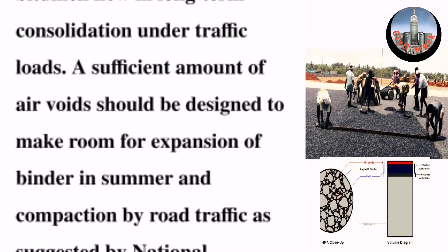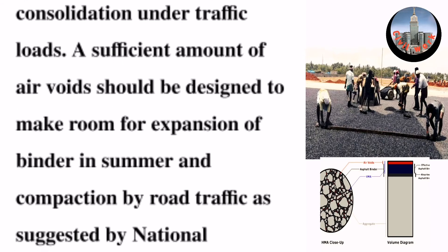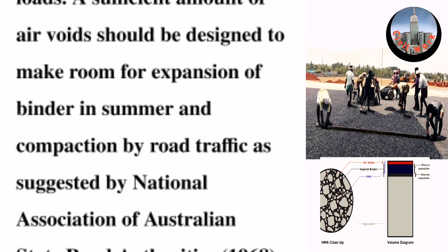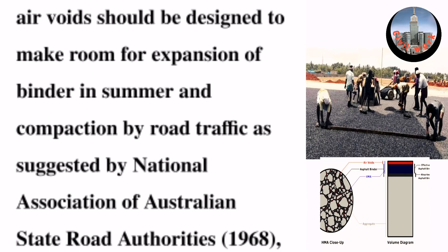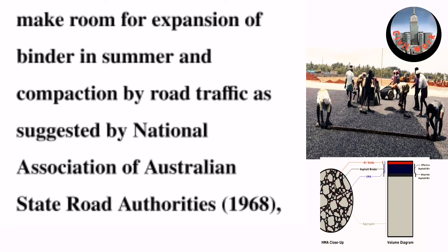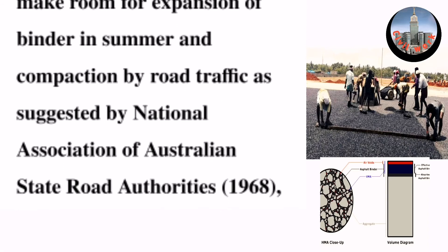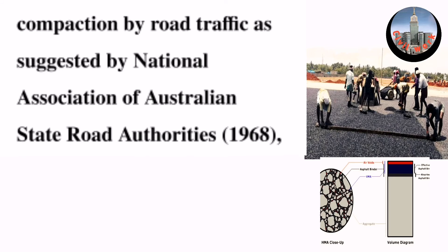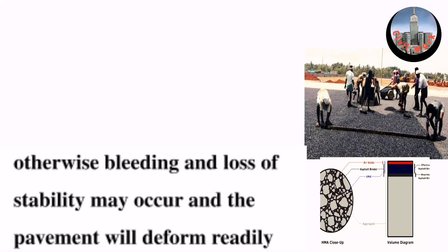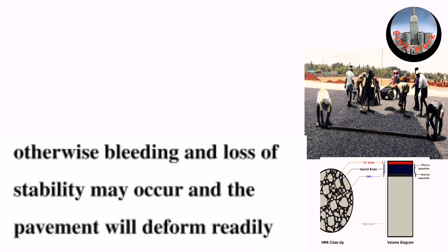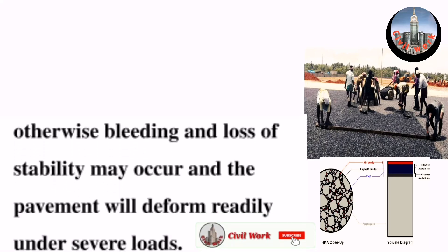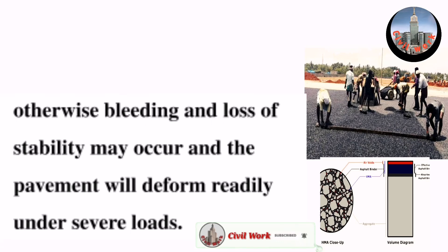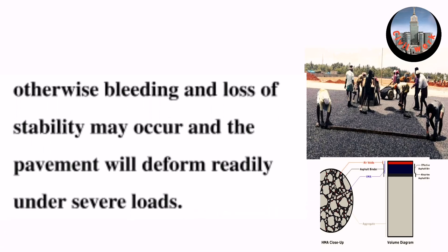A sufficient amount of air void should be designed to make room for expansion of binder in summer and compaction by road traffic, as suggested by the National Association of Australian State Road Authorities (1968). Otherwise, bleeding and loss of stability may occur, and the pavement will deform readily under severe loads.